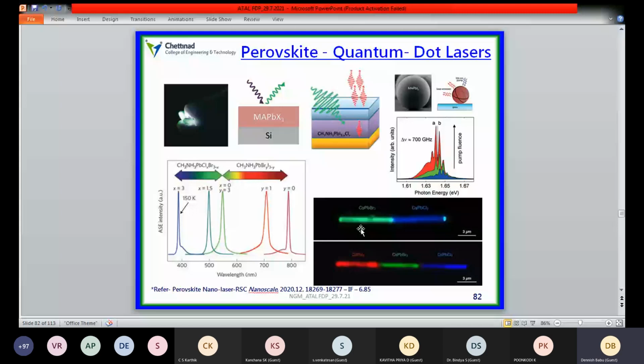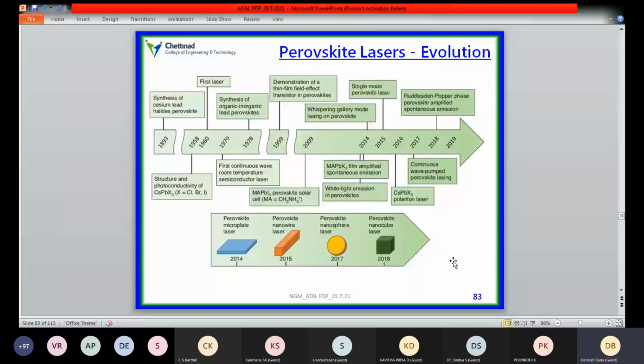The evolution of the perovskite laser started in the year 2014. Earlier, people identified cesium lead perovskite as a material in 1893, and after that started to identify its photoconductivity property in 1958, and after that the first laser was invented with helium, neon, and other materials. The first perovskite based laser was introduced in 2015. Single mode perovskite lasers were identified and used, and after that people have used many two-dimensional systems, Ruddlesden-Popper and Dion-Jacobson phase based perovskite materials for lasers, especially continuous wave pumped perovskite lasers.